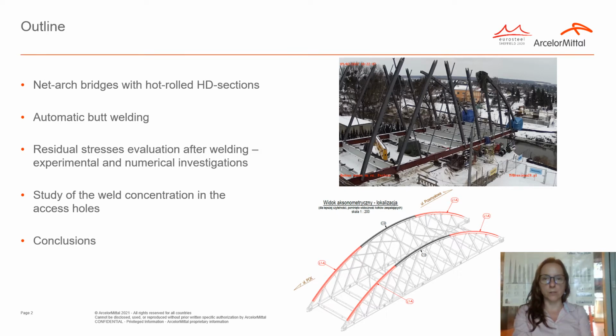arches of arch bridges. An experimental campaign consisting of the automatic butt welding of the splices is presented in order to provide guidance on how to weld profiles with thick flanges and calibrate numerical models in terms of residual stress evaluation after the welding. Access holes need to be provided when welding such profiles, and a measurement of the residual stresses is proposed and compared with numerical results.